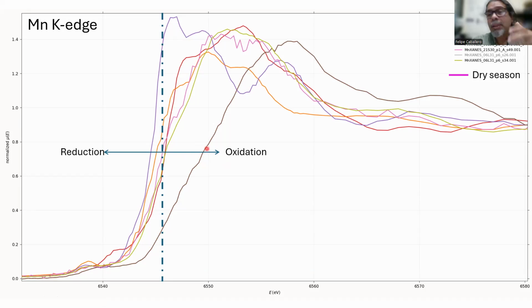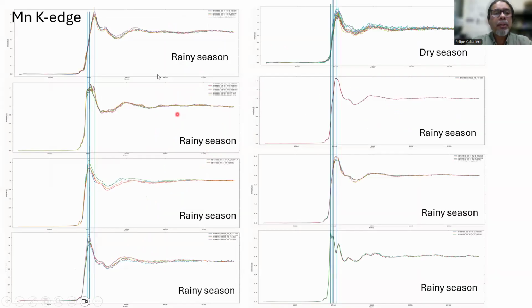That is very important because redox reactions can occur in the presence of moisture, and can be associated, for example, to chromium oxidation and manganese reduction. As you can observe here, the manganese K edge has at least 8 different shapes, depending on which particle we measure. So in the same sample, in the rain samples, we observe all this variety of manganese oxidation states. Some of these states are more toxic than others, as we discussed before. But in the case of the dry season, all the manganese is the same. So during the rainy season, the moisture in the powder changes the oxidation state, also interacting with the rest of the metals in the sample, particularly chromium.